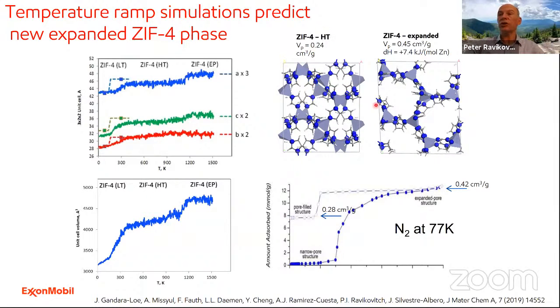So there is a strong indication that this expanded structure does exist, and in simulation, it has been stabilized by entropy. In experiments, it has been stabilized by adsorbing nitrogen molecules.